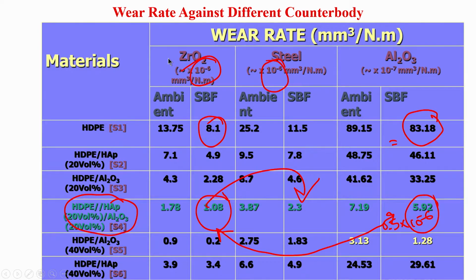Now when you go to 0.2 to 1.83, again 9 times higher, and if you go to HDPE 20% alumina, it again goes from 2.28 to 4.6, so again it is like 2 times higher.